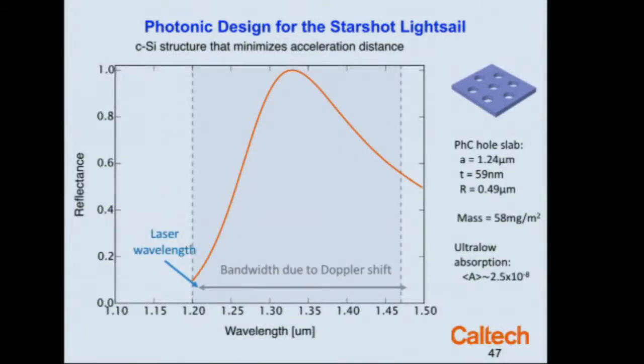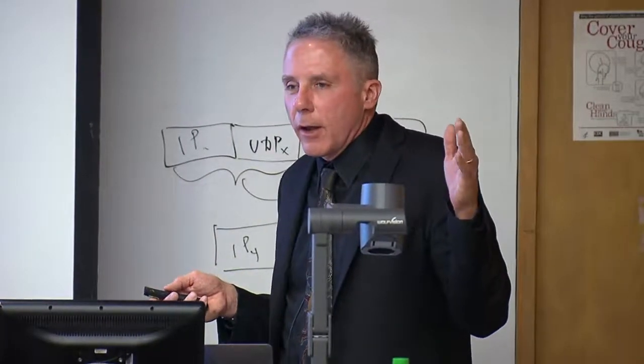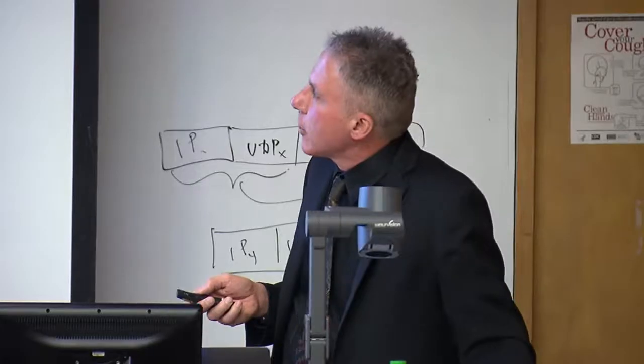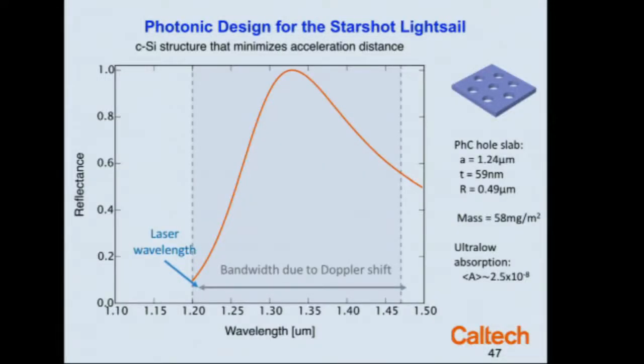And this actually, surprisingly, you would have thought perhaps the optimal one would have a reflectivity of 99.9% across this whole band. This is the reflectivity of the optimal structure. By giving up the weight, we were able to sacrifice what the optimal solution told us we could. So this tells you that multivariate optimization and learning can lead you in counterintuitive or non-intuitive directions. This is the reflectance profile. It's actually not very reflecting at all until it gets up to here. It's not even 100% here, and it goes down. And this is the entire bandwidth over which the sail experiences the light as it accelerates.